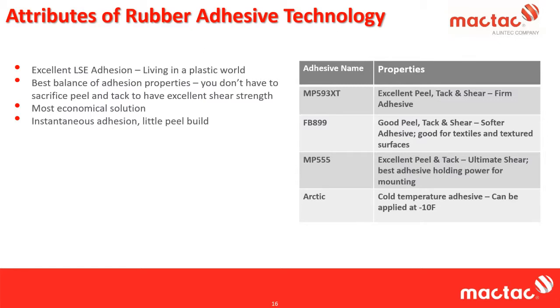And we do get instantaneous adhesion with little peel build. So there may be some familiarity with some types of acrylic adhesives that do take up to 24 hours to build their permanent bond strength. Rubber-based adhesives really give you that performance almost immediately. We also find that rubber adhesives are underutilized in many applications. There are a lot of folks who believe that acrylic adhesives are superior, and in some cases they are required. That is most certainly true. But a rubber-based adhesive can really meet, I would say, 95 to 98% of the applications that we come across on a daily basis.